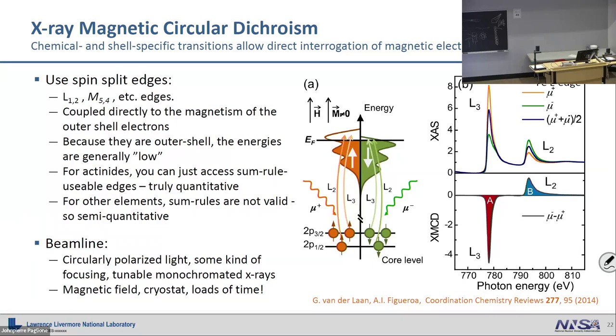And then when you scatter into this area, you have unoccupied states. The number of unoccupied states is how big this white line is. So you can see I scatter here and I get this big white line. If I switch my polarity to go the other way on my incident photons, I'm going to scatter preferentially here, and I get this lower white line. So I get a difference between my X-ray absorption spectra with my polarity going in, and that's called XMCD. So you basically take the difference of those, and that's XMCD.